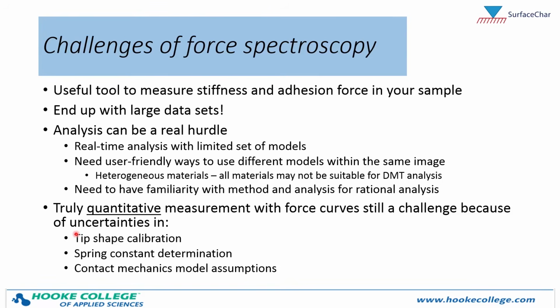And I'm going to conclude by saying that truly quantitative measurements with force curves are still a challenge because we still have significant uncertainties in our main calibrations of the tip shape. I always say in my courses that the tip shape is the Achilles heel of quantitative nanomechanical measurements with AFM. Very hard to measure it, and even if you can, it will change on you. Also, the spring constant determination. We definitely have some uncertainties in the spring constant determination, so that affects these calculations as well. And finally, our contact mechanics models are simply that. They are models. DMT and JKR are big improvements over Hertz, but there are many materials that I myself have looked at that really neither model is appropriate for.